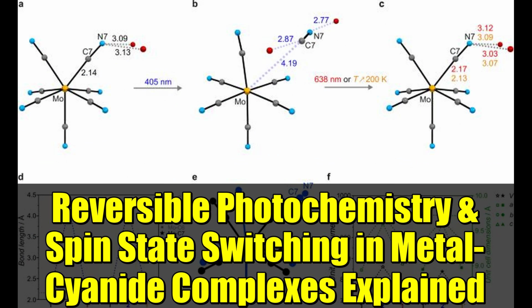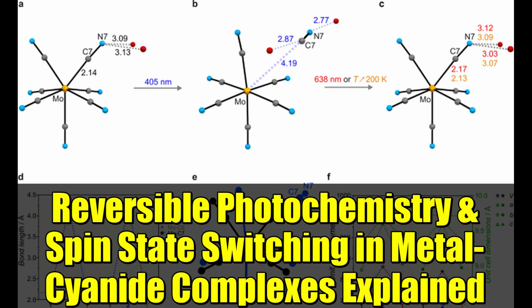Collectively, these photomagnetic experiments at 10 K suggest thermal trapping of the S = 3/2 metastable state, analogous to spin crossover systems, confirming the formation of a light-induced high-spin heptacyanomolybdate complex. As the temperature rises, the photo-induced state relaxes to the original S = 1/2 ground state of the [Mo(CN)7]4- complex around 150 K, indicated by a sharp drop in the χT product.